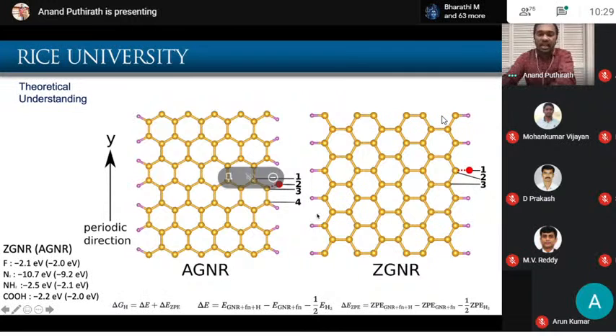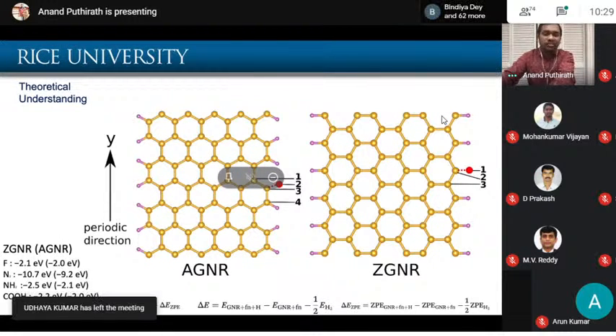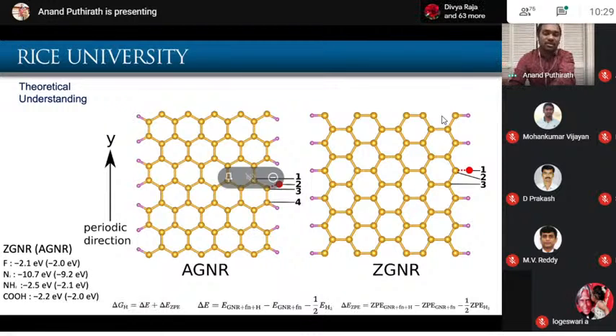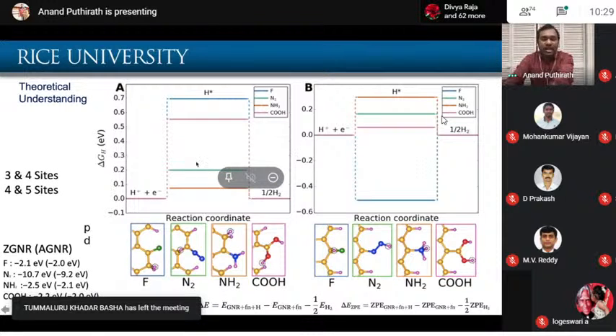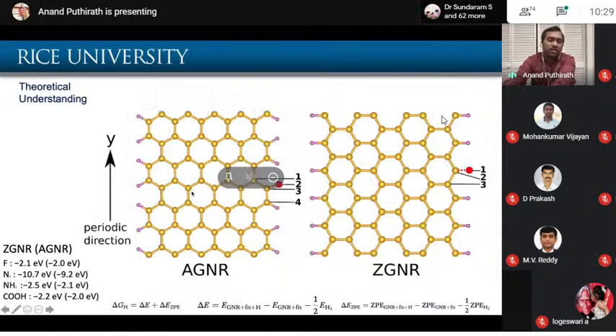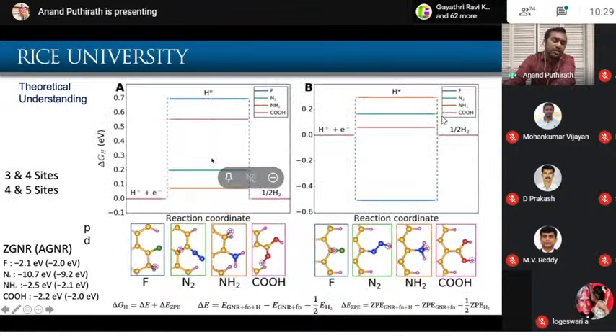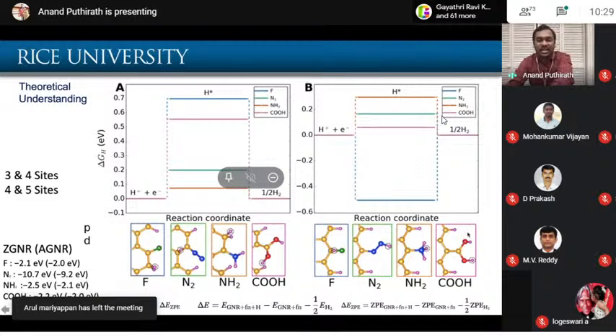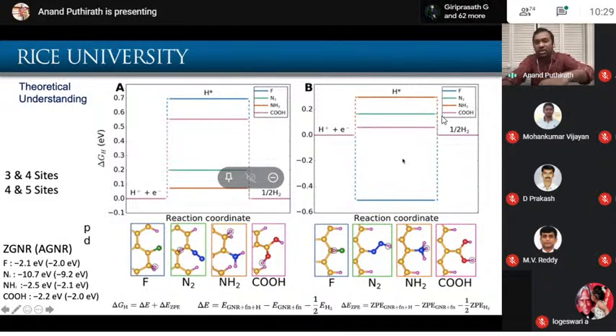So that's the case. And what we study is the free energy change during this adsorption desorption phenomenon that happens to a system. If a system has the least delta G change in the adsorption desorption, it is a better catalyst, but it may not be a good supercapacitor electrode, because we need two different things for both the cases. And unfortunately, this armchair modeling never followed our experimental results, which simply means that whatever material we have, it has zigzag edges. But the zigzag edge system, this is DFT modeling, really followed the trend that we have seen in the experiment.